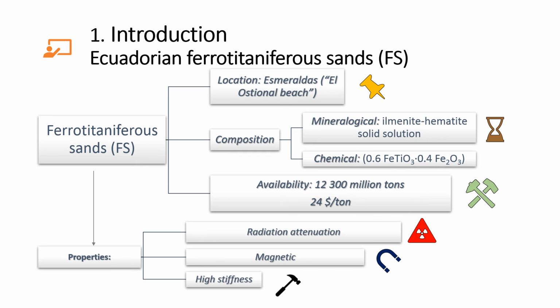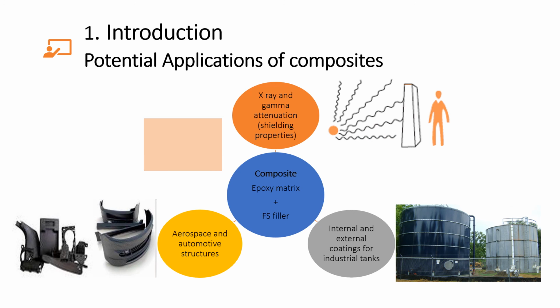As a matter of fact, solid solutions between ilmenite and hematite both display semiconducting and ferromagnetic behavior, resulting in a non-traditional magnetic semiconductor with conceivable spintronic and ionizing radiation barrier applications. Hence, this work is intended to evaluate the effects of ferrotitaniferous sands in reinforcing an epoxy resin through micro-indentation and dynamic mechanical analysis. This study is a framework for the exploration of the mechanical and thermal responses of the as-prepared composite, a valuable step towards expanding the application of the ferrotitaniferous sands in this research area.